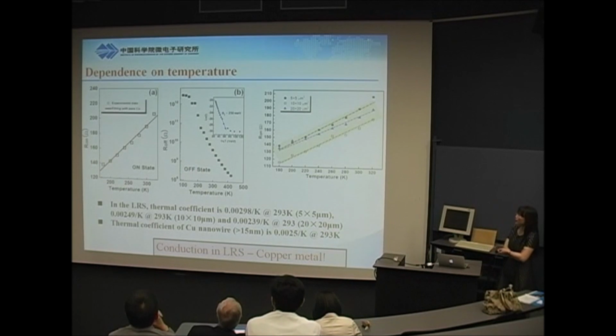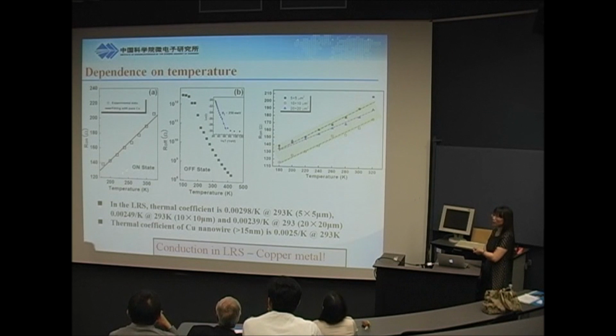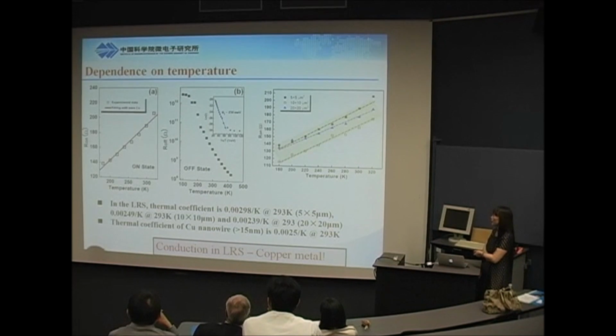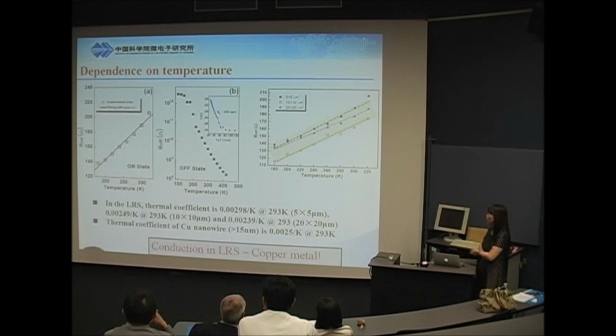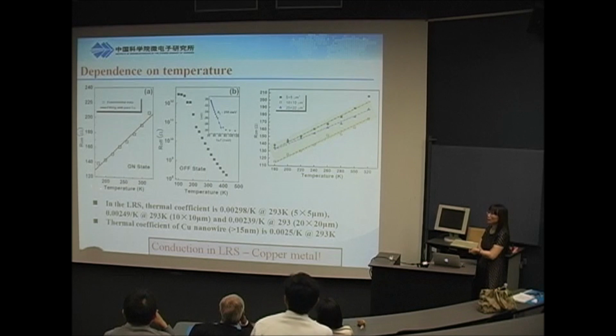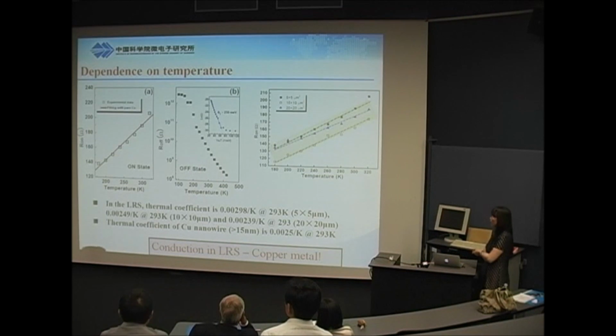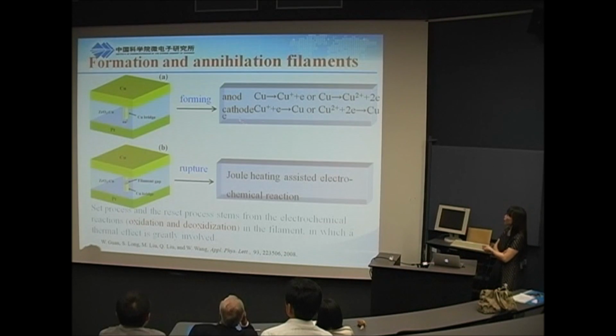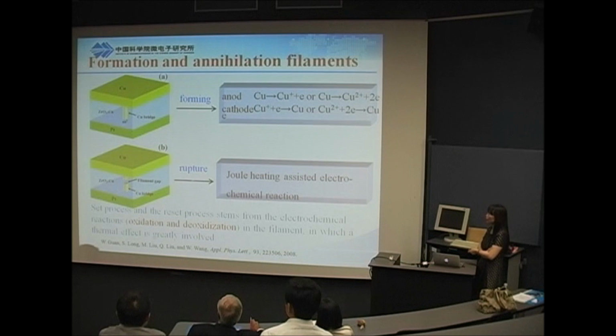So next, we did some temperature dependence measurements. For the on state, the low resistance state, the thermal coefficients of different devices are almost the same. We compared them to a copper nanowire, and they are similar in value. So from this experimental result, we can see that in the on state this filament is consistent with copper. Based on this, we propose the forming process: the copper filament is formed between the top and bottom electrodes. For the reset process, this filament is broken, going from the on state to the off state. But this is just deduced. To really understand, we should take TEM pictures to observe this process.